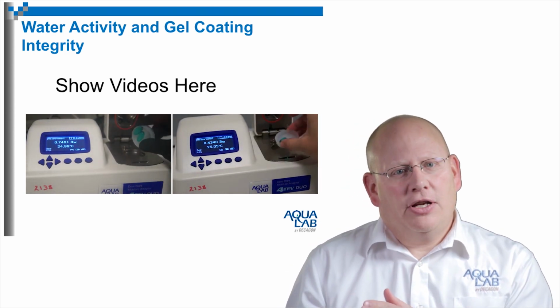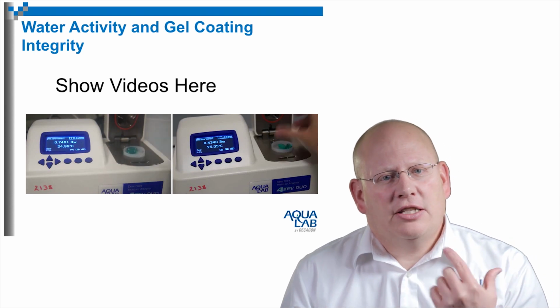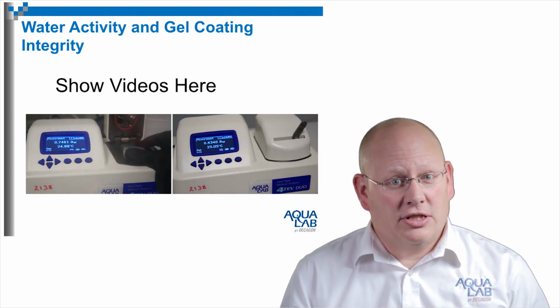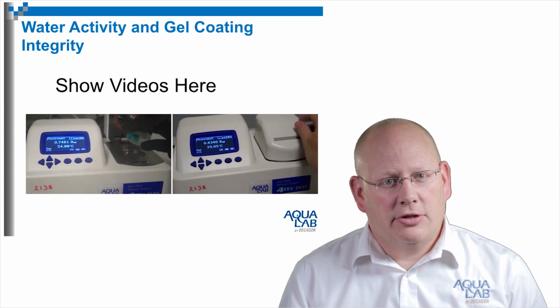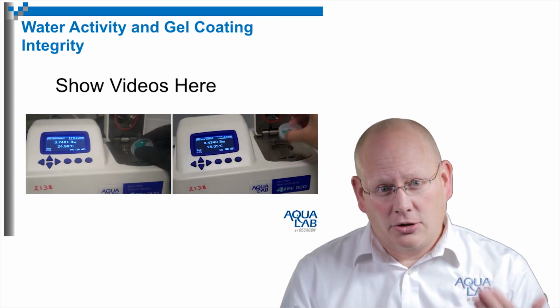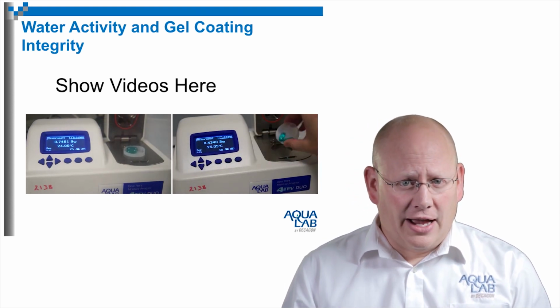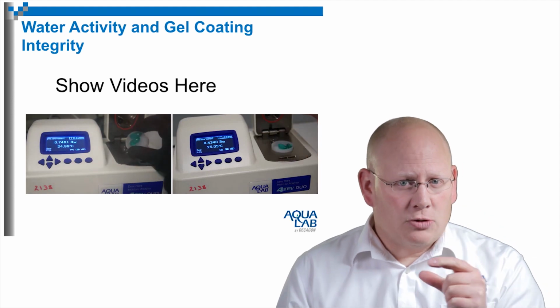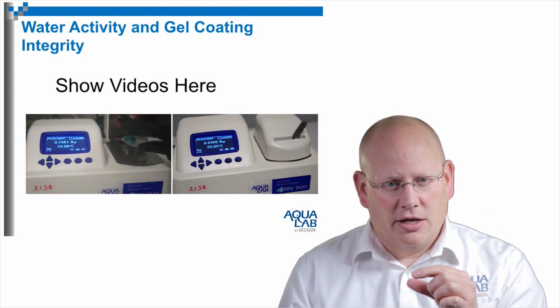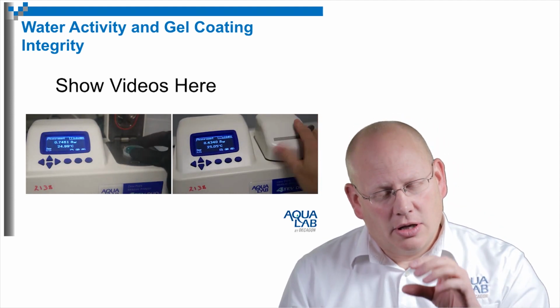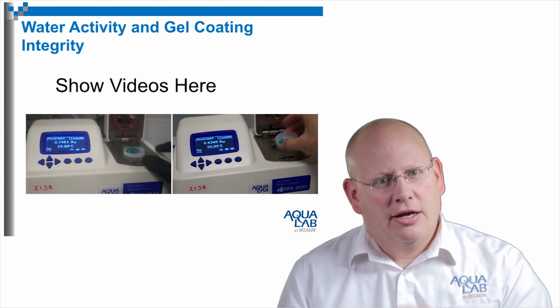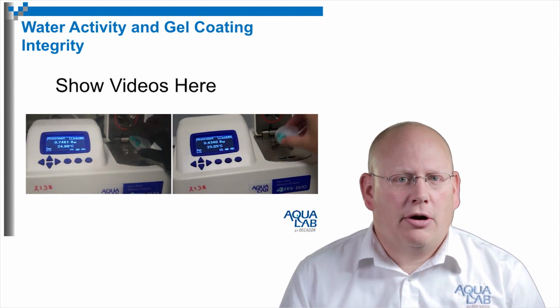Now in the second video, you can see that the water activity of the gel caps has been increased. It's been exposed to 75% relative humidity, meaning its water activity has increased to 0.75. You can see at this water activity, as the cup is shaken, those capsules stick together, and that's because of exposure to high water activity.